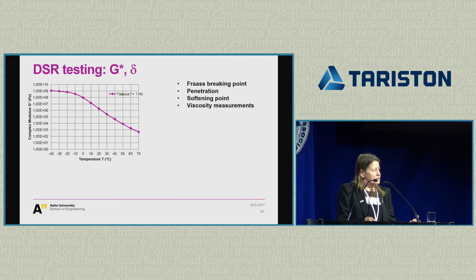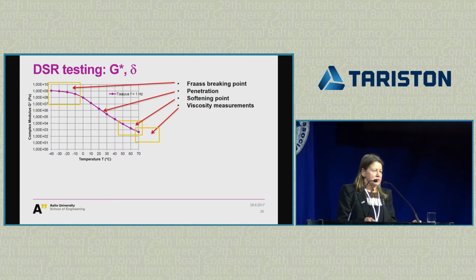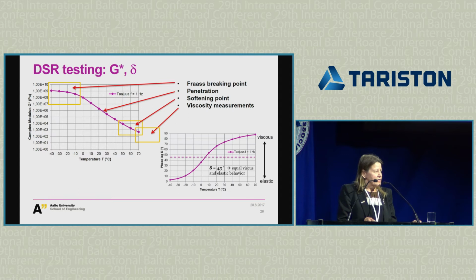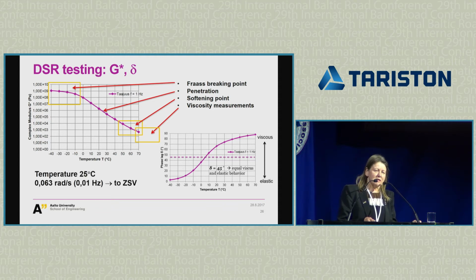So we have DSR testing. Fraass breaking point somewhere here, penetration somewhere here, softening point, and then we could also use this for viscosity, but it's a high temperature viscosity, and we really don't want to be in high temperatures. We've started to come to the conclusion that we need to be in lower temperatures. So we have selected to do the calculations at 25 degrees Celsius, anyway trying to shoot for the zero shear viscosity